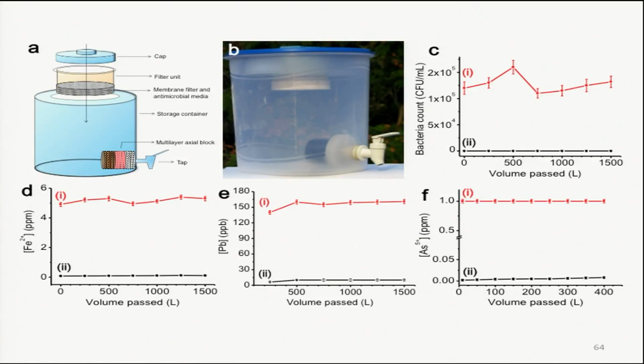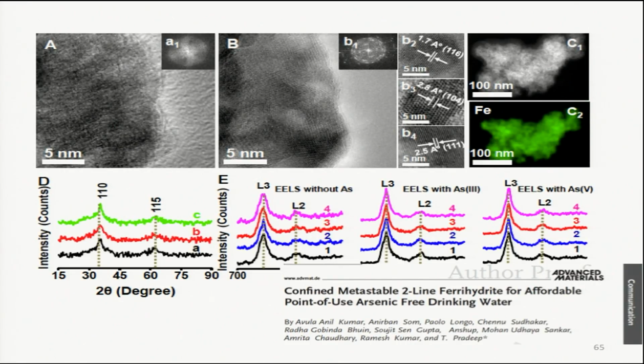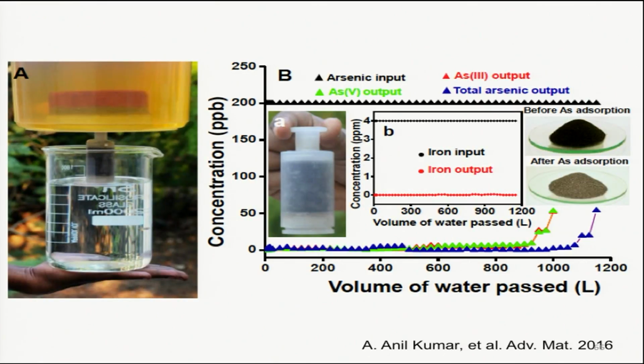Now in this kind of thing, you are leaching out silver ions into water, and this water is interacting, or these ions are interacting with bacteria. When this water containing metals or contaminants pass through another filter, this filter removes the contaminants other than bacteria. So we have to create multiple materials. So Anil, sitting in this audience, he made a very interesting nanoscale material. This is, of course, you do spectroscopy at a nanometer level to prove what kind of particles are present. But most interesting aspect here is that you can put this material in a filter like this, pass contaminated water through this. This is iron and arsenic containing water, and you can get that.